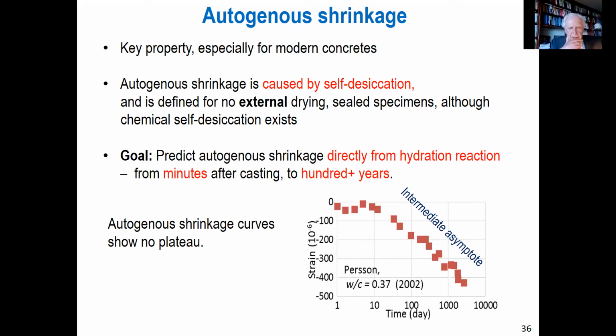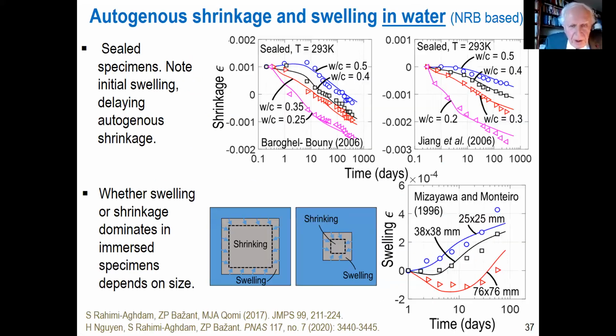Next comes autogenous shrinkage. I already said that it goes probably forever in the logarithmic scale. So this is actually a semi-log plot published by Persson from Gothenburg. He measured for about 10 years, and it does not end in a few months as assumed from linear scale plots, but actually goes and goes on and on. No plateau. There eventually has to be a plateau because they run out of reactants, but that can be centuries away. So as far as we know, there is no plateau.